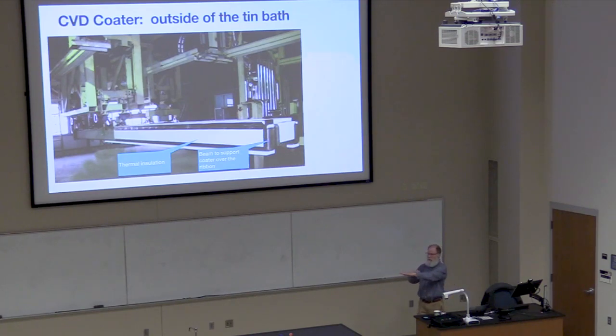So you've got to put the metal beams in, and they've got to be water cooled. So those beams are water-cooled channels in there. The problem is they're going to cool the glass, so you've got to insulate those really well so they don't cool the glass. Then the coater is behind that insulation, so you can't really see anything.